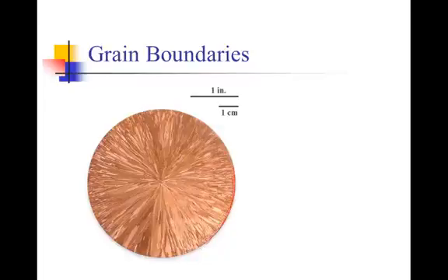You see all those little tiny crystals in there, and not many crystal nuclei want to form in the center, because that's forming a solid out in the middle of the liquid, and there's a large surface energy associated with doing that. So instead they form on the solid wall, and then they all begin growing towards the center, eating up the liquid as it cools, and that creates really large crystals, and it makes for a weak material.